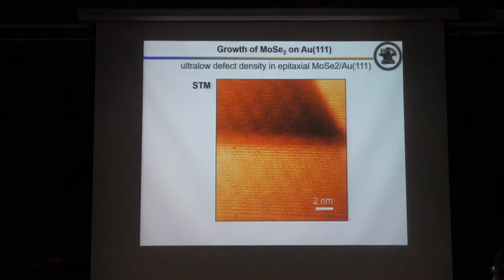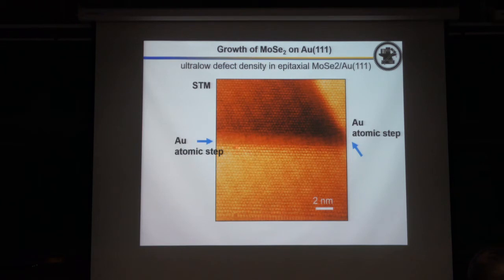And we also try to use STM to identify the defect density. As you can see in the image, this is an atomic step of gold. You can see this darker area, this brighter area, and you can see this is an atom of MoSe2. Here we have one defect. This is a vacancy. Another defect here. And if your eye is good, here is another. So we have three point defects. If you calculate the area, the structure defect density is about 4 times 10 to the 11.